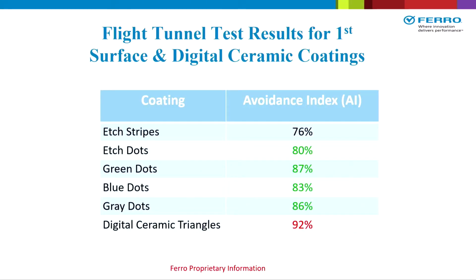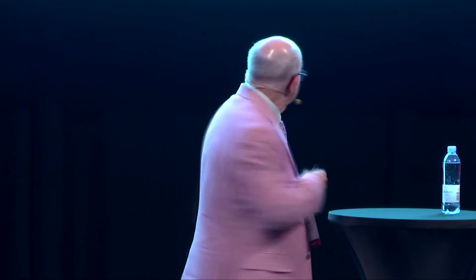So now we're going to take a look at the score, which you already got a sneak peek of a minute ago. And we can see that all of the coatings are usable for the LEED credit. You got a 76 for the stripes, but then 80s for the dots, and 80 and above for all the dot patterns. So they're all most preferred. But then the shining star of it all was the digital ceramic print with this 92.